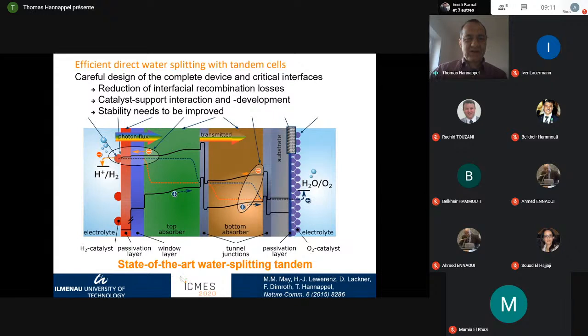Then, in addition, we need the interaction of the electrolyte and the device structure. For this, we might need passivation layers. We need firstly to passivate against non-radiative recombination. So we do not want to destroy the electron-hole pairs, which we have created with light, by destroying them and converting this again into heat. This is what we need to avoid strongly. And in the next step, we need the chemical passivation, so we do not want to destroy the device structure. So this is the protection against the electrolyte, which might dissolve just simply the device. So this is also a great challenge and a functionality which needs to be improved.